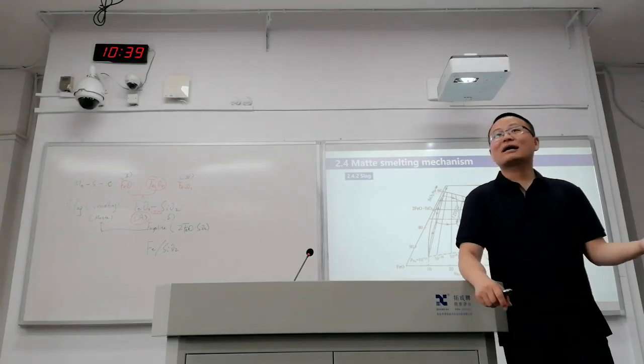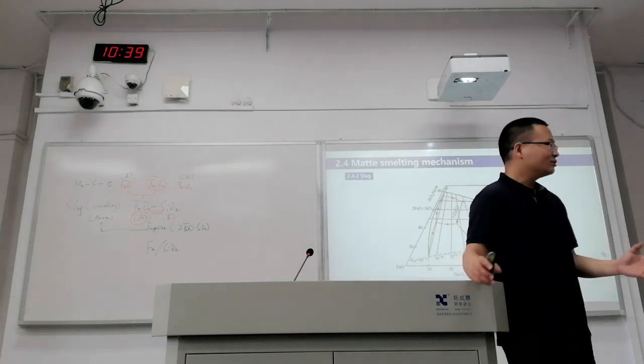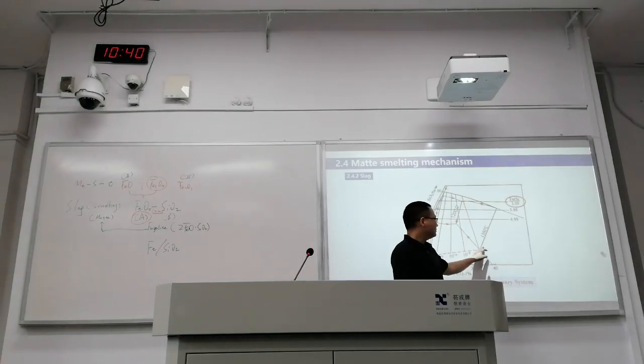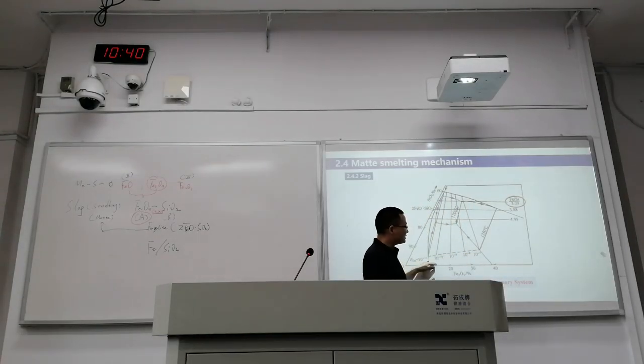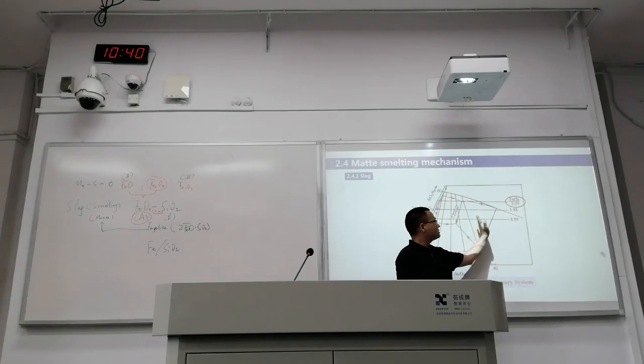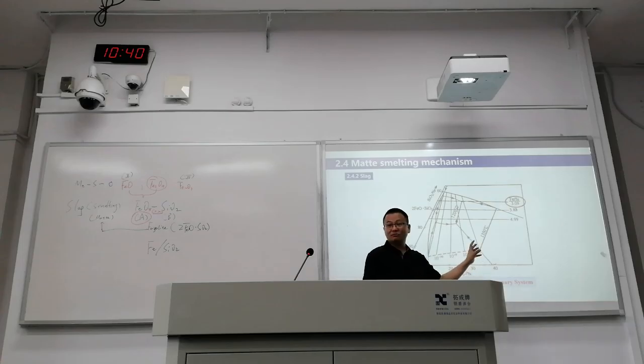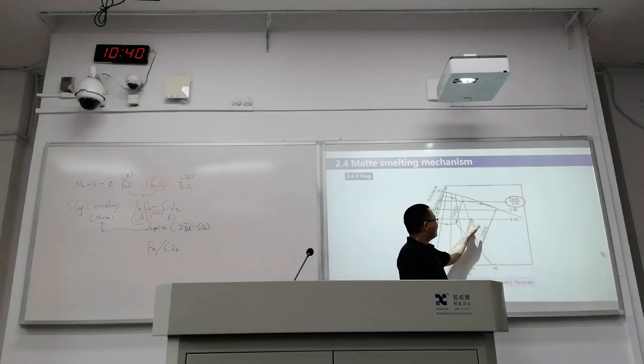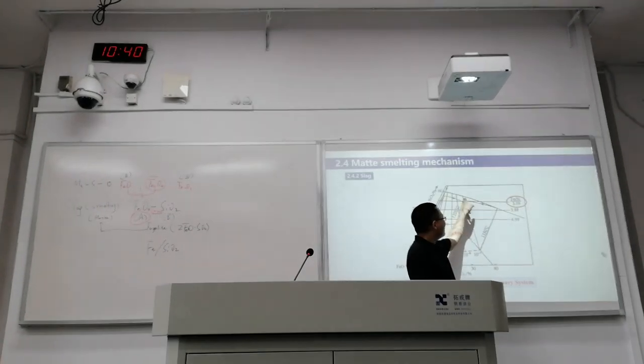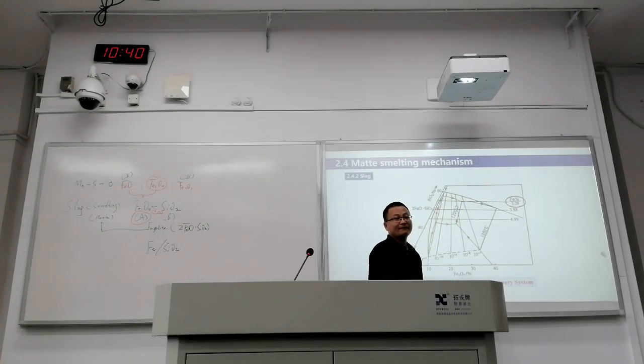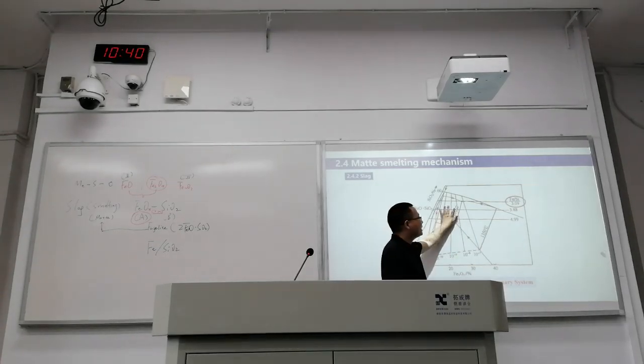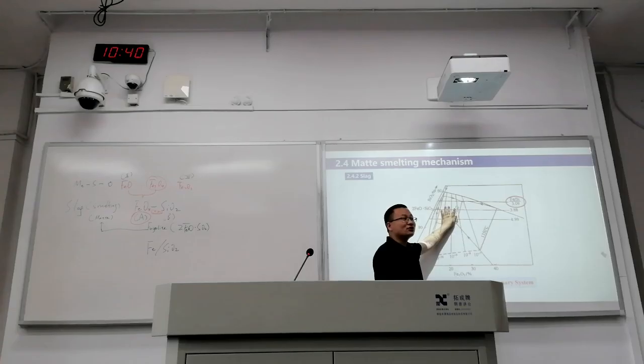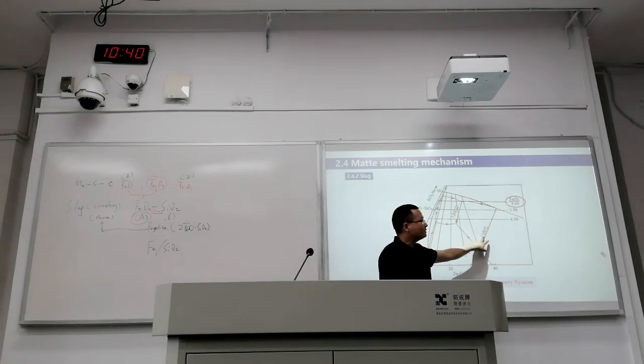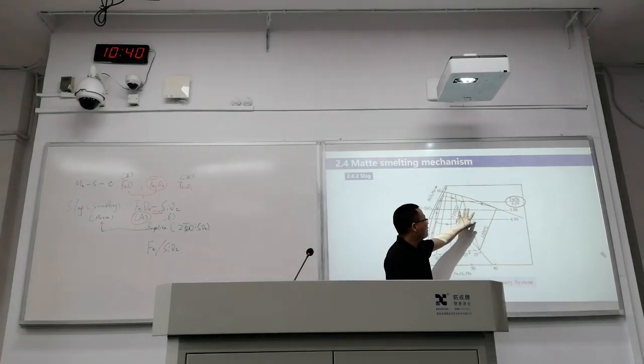You are getting something else. You are getting oxides, you are getting sulfides. So you are not having that. So these two should match very well. If you are having such oxygen potential, this is the tendency. So if you want to have -6, -5, you are somewhere here. Okay, so let's take 10 to the -7 as an example. This is a line, so it will be outside of 1200 degrees C. What does that mean? This is not our option anymore. So we have to push it to 1300 or something else. If we are having 1350, we have big regions, right?